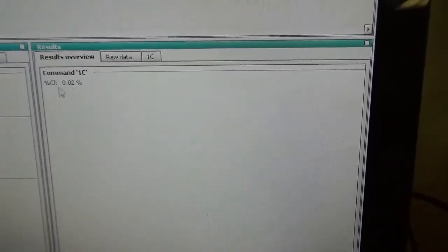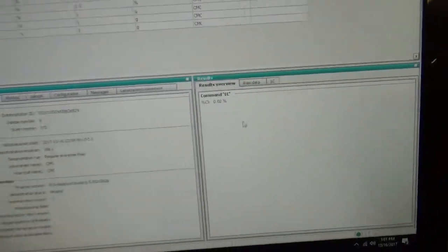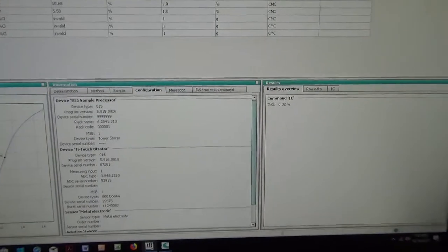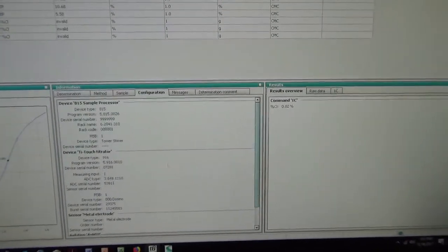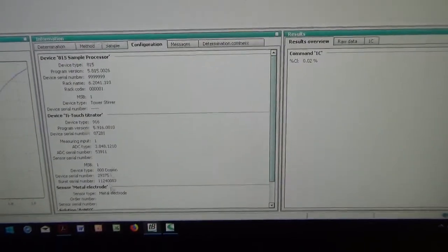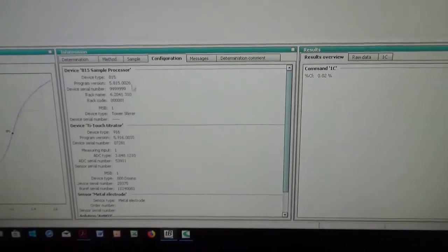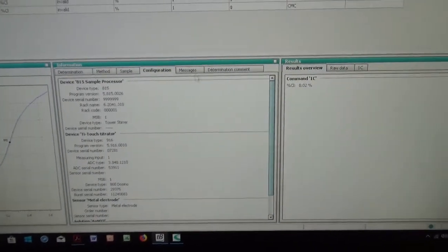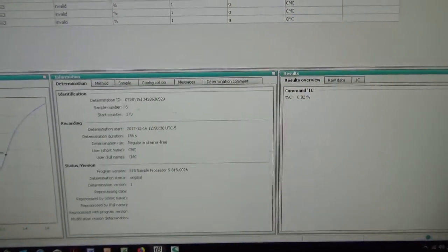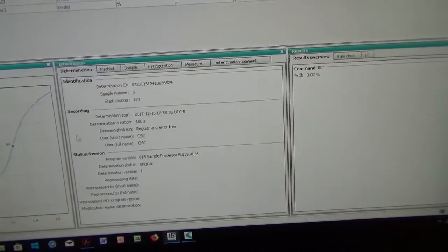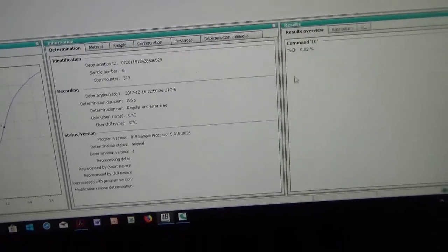0.02% by mass of concrete. It gives the chloride content. It also gives the details of the method, the configuration, and which equipment was used: 916 Ti-Touch with 815 sample processor. So this is how the whole result comes, and then it gives the whole report from that.